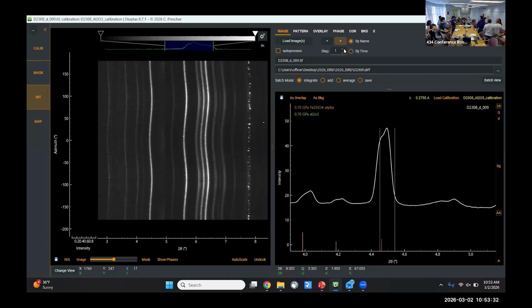But this one, now that the planes are closer together, the crystals that are oriented this way will diffract, say here. Because they're closer, it'll diffract at a wider angle and they'll come out higher. And then the grains that are in between will be somewhere intermediate. So what originally was a circle has now become an ellipse. That wasn't a very good ellipse, but do people understand that concept? So we're squeezing it harder in one direction. The planes are getting closer in that direction, so they diffract more. So our circles become ellipses.